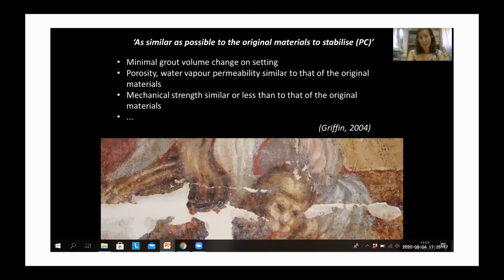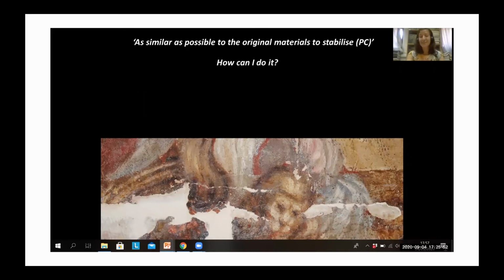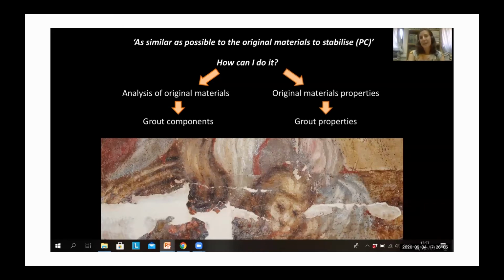We know that wall paintings are always very porous systems. So we want porosity and related properties, so water vapor permeability, capillary water absorption, which are similar to those of original materials, and other properties such as mechanical strength, similar to that of the original materials or less. We don't want something which is much stronger than what our original materials are. And how do we achieve this? We do an analysis of original materials, and with such information, we can have an idea of the grout components we might want. It would be ideal, but is not always possible. It's rather difficult. It would be ideal to know the original material's properties, so that with such information, we can also tailor what properties we want from a grout.